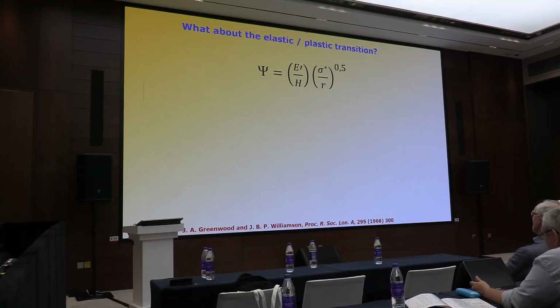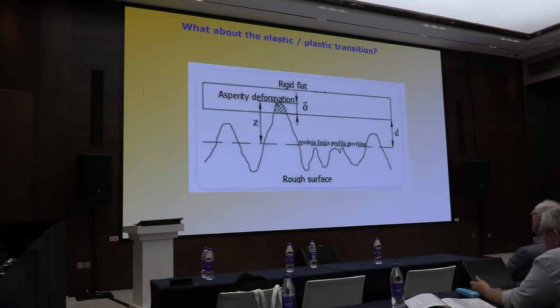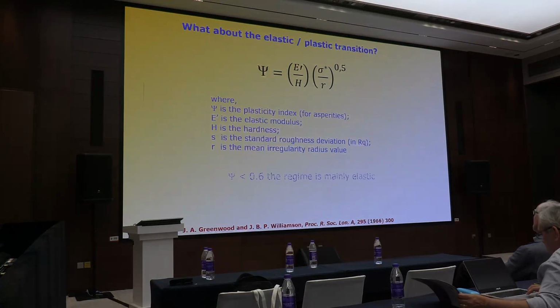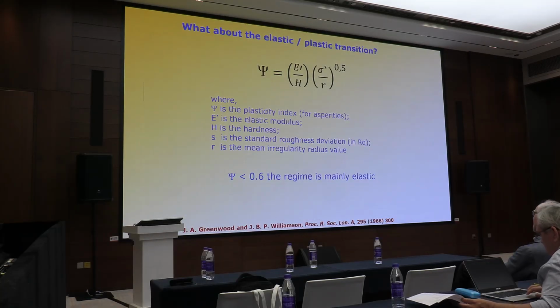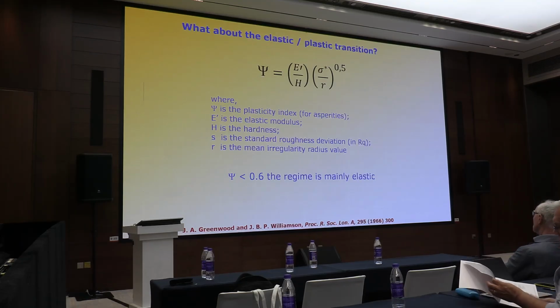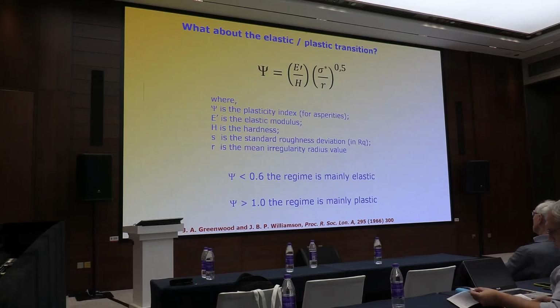It's difficult because this is the radius. We have to know the roughness, and then the curvature of the asperity at the top of the mountain. This is the mountain, and we have to know this curvature. If we imagine it as a sphere, we have to know this radius. With these parameters, if this index is lower than 0.6, the regime is mainly elastic, and if this index is higher than 1.0, the regime is mainly plastic. This is a very easy and straightforward way to know whether we are in the elastic regime or the plastic regime. Good.